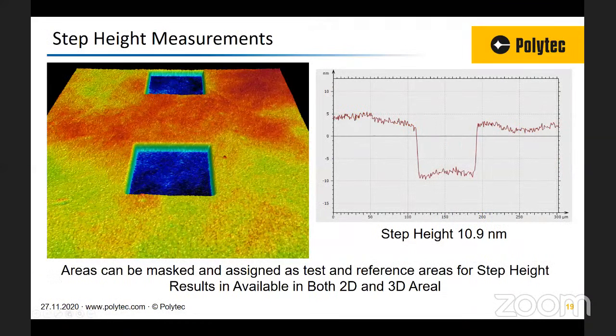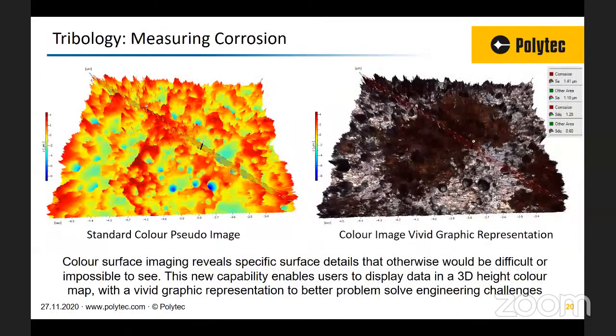So we're ideal for measuring small step heights. Here we have a small step height in the order of 10 nanometers. We can measure tribology. Here I have an example of measuring corrosion. The image on the left is how a typical pseudo color image would be viewed. But of course, this is a corrosion measurement. The image on the right is a vivid graphic representation in colour of how this surface appears on the Microview Plus. And here you can see much more clearly how the surface texture is changing in the corroded areas to the non-corroded areas.